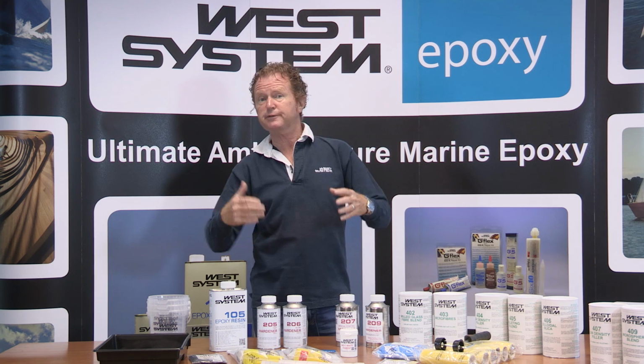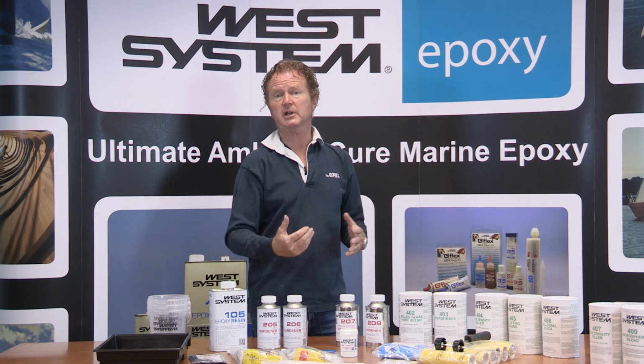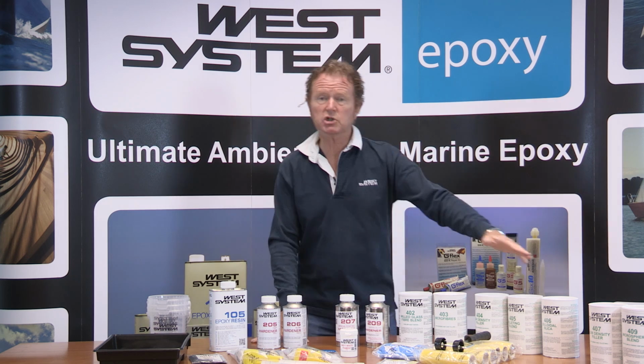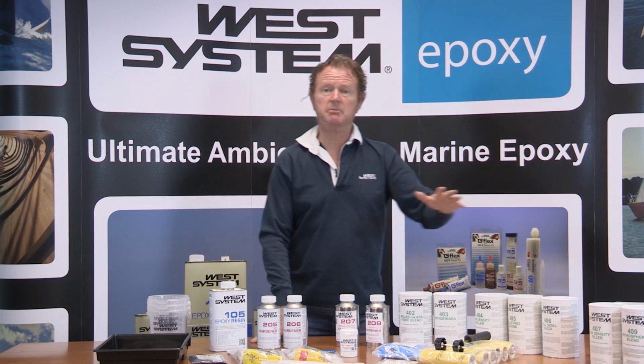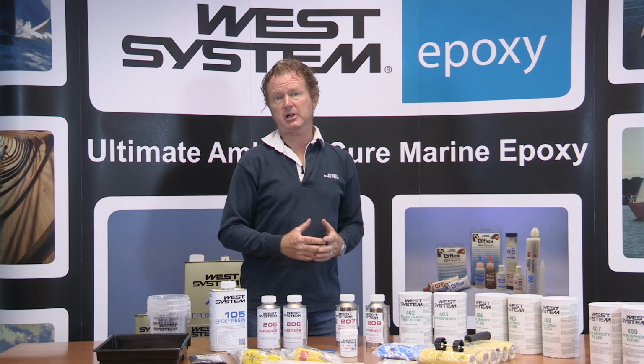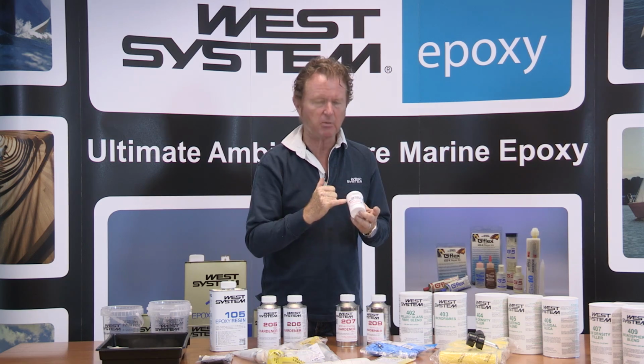Our low density fillers are still incredibly strong, but they make sanding the filled mix a lot easier. So if you are filling a surface, in other words, filling a rough surface to make it smooth, you would choose a low density filler because it makes the task of sanding that much easier. We do have a range of pigments. These will pigment the mixed epoxy, but they won't create UV stability. Here we have our white pigment, but we have a range of three other pigments, blue, grey, and black. And they can be mixed with a small percentage to the mixed epoxy resin, and they will colour, but remember, they do not possess UV stability.